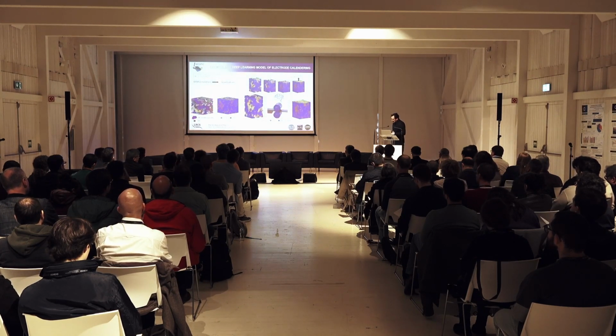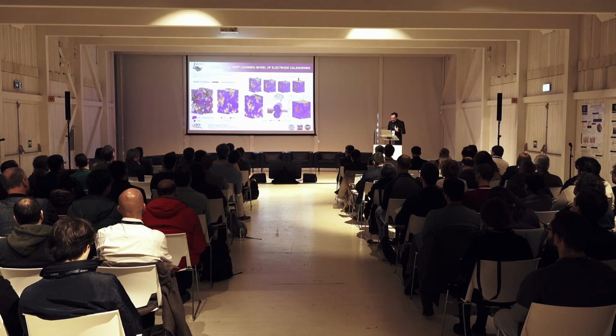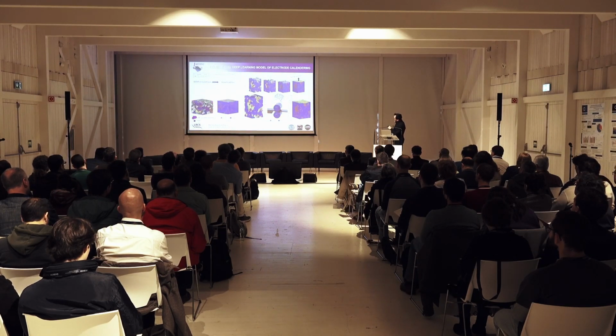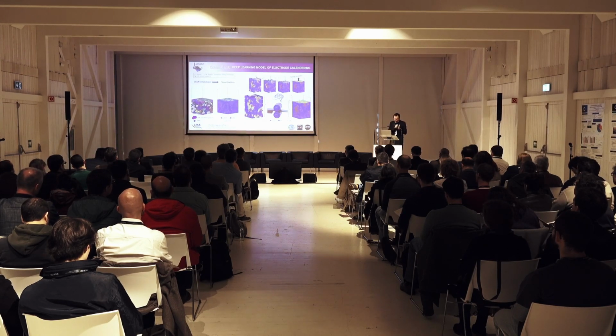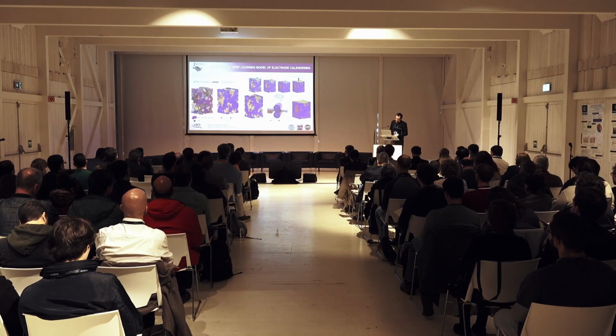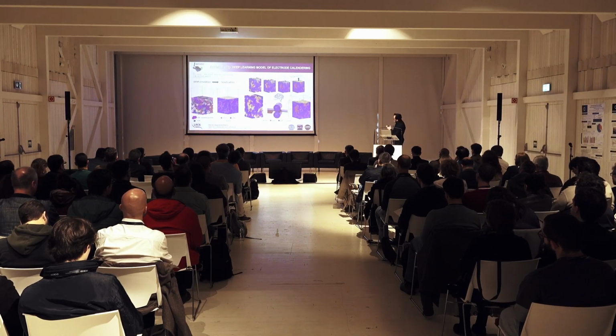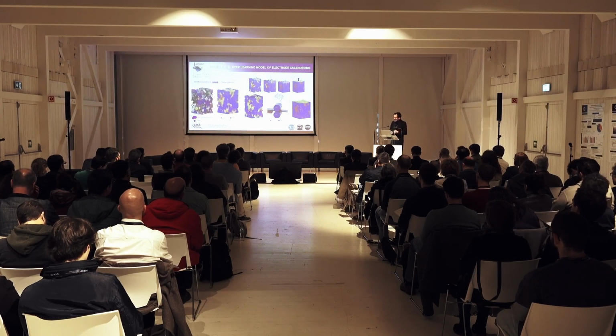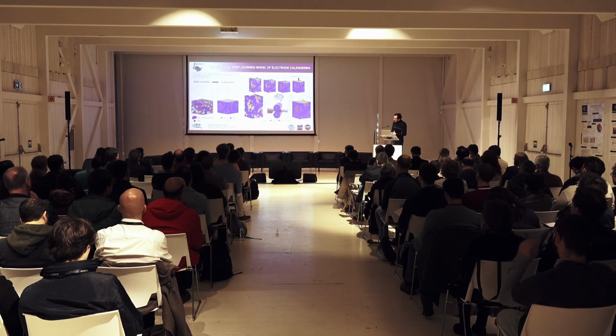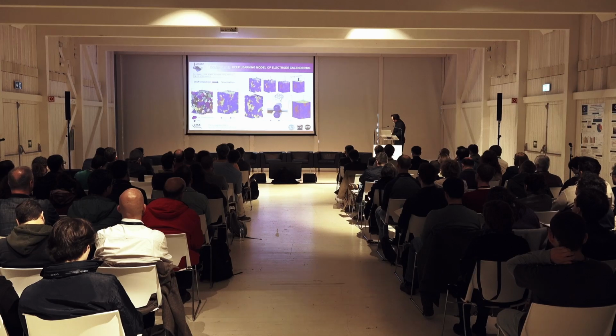And here, basically, what we have done is we have collected data arising from the discrete element simulations of electrode calendering. We have voxelized these simulations of the electrode compression and the spin back. And then we use these images, which look more like a time series of images, to train a convolutional neural network model. And this convolutional neural network model is now able to simulate this calendering process much faster than what the original discrete element model is able to do.